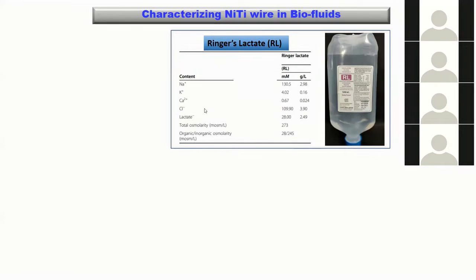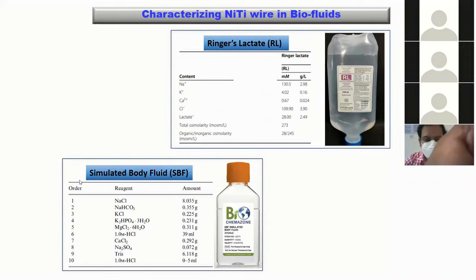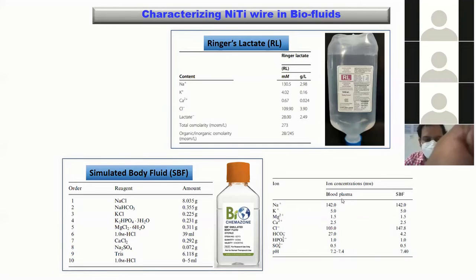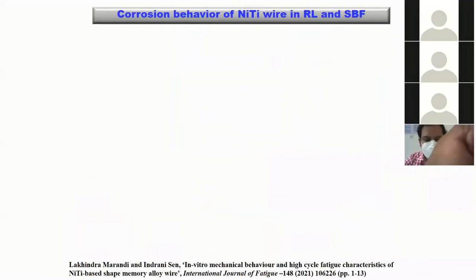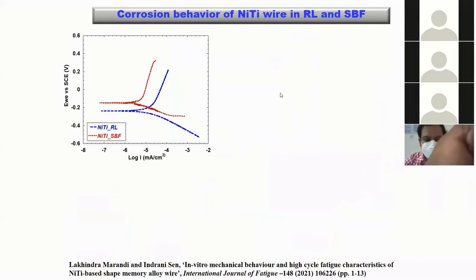So we chose biofluids to work with. And the first thing that we used is Ringer's lactate. Ringer's lactate is nothing but the saline solution that we use, if you have ever come to the hospital for this. This is the saline that is hung for us. And the second thing that we used is a simulated body fluid, which has a composition very similar to the blood plasma. Okay, so what we did is we immersed this wire specimen into this Ringer's lactate and the simulated body fluid, and we have done the corrosion test of this.